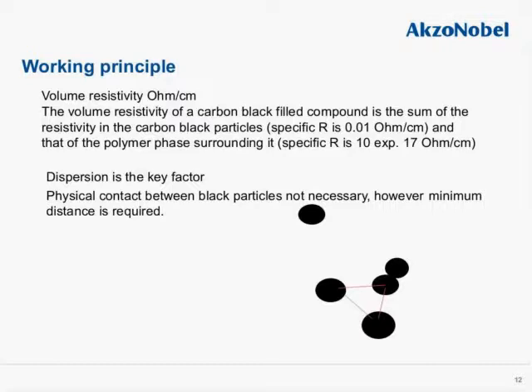Principle. If you remember from the picture shown before, the amorphous structure will be grabbing onto each other, individual carbon particulates. So in order to conduct electricity, those particulates have to be either in touch with each other or at a very small distance. Therefore, the so-called electron tunneling, the electron jumping from one particulate to another, is facilitated. If they are at a further distance, then the electron cannot jump from one particulate to another, and therefore electricity cannot flow through. Needless to say, in order for a polymeric compound containing Ketjenblack product to be conductive or to have an anti-static property, dispersion will be the key.